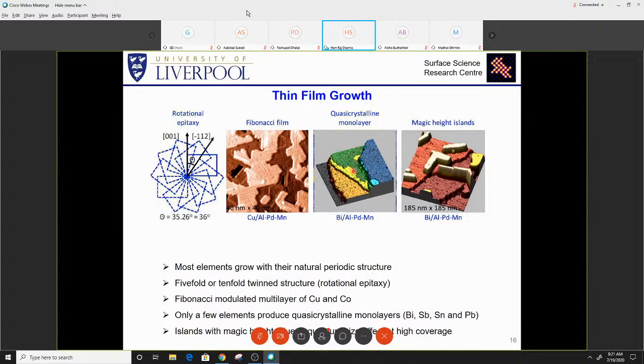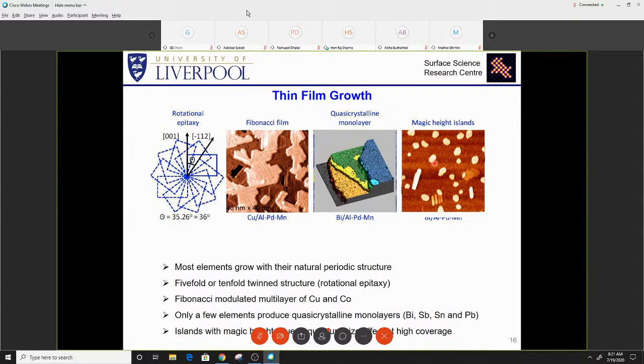So what happens if you put more elements on the surface? Then you start. Again, you can already guess it. Using STM, you can really see how it goes. You can see some islands are more stable than others. This island disappears and this will go. The stability of specific islands is due to quantum confinement.